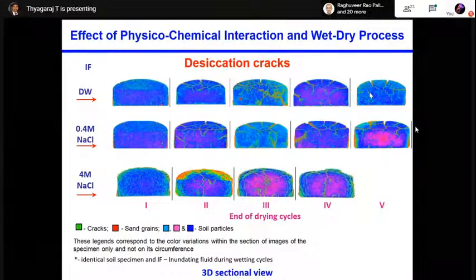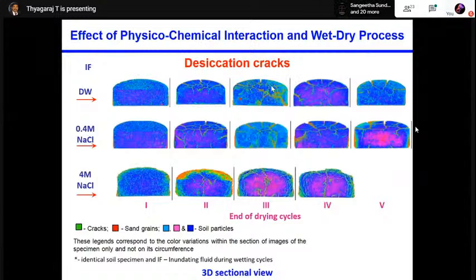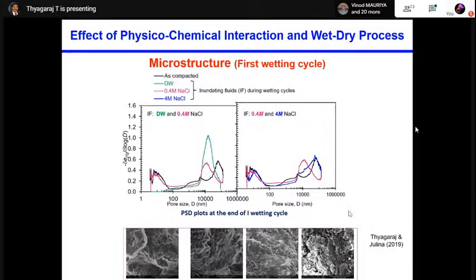Why is it so? Because the healing of the crack is taking place in case of distilled water where we do wetting and drying. But whereas with 4 molar NaCl solution, the healing of the crack, even though it occurs, is not occurring completely, and the crack occurs at the same place. So for that reason, we have also studied the structure using the MIPs.